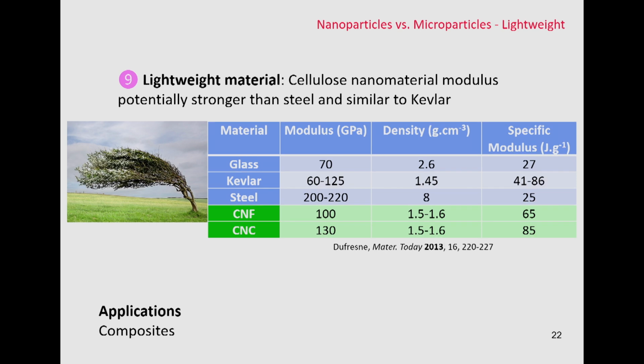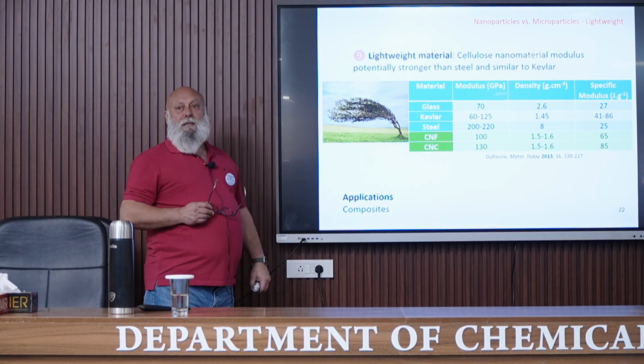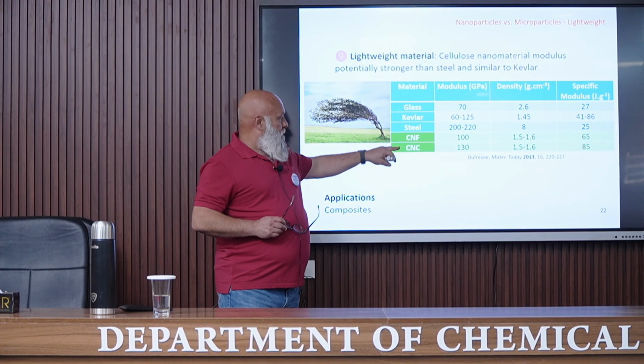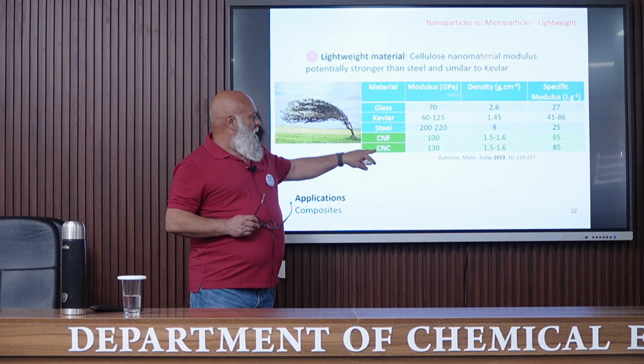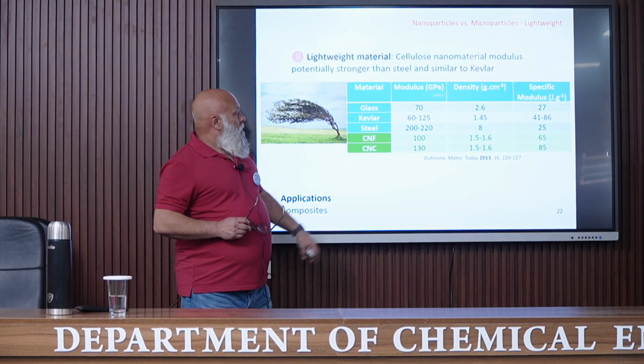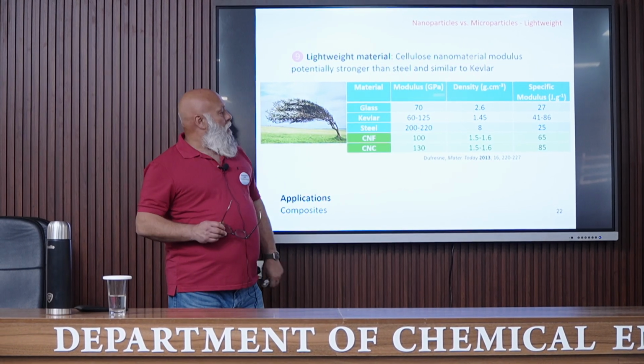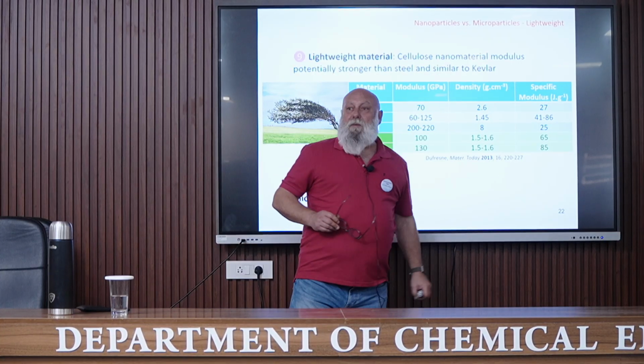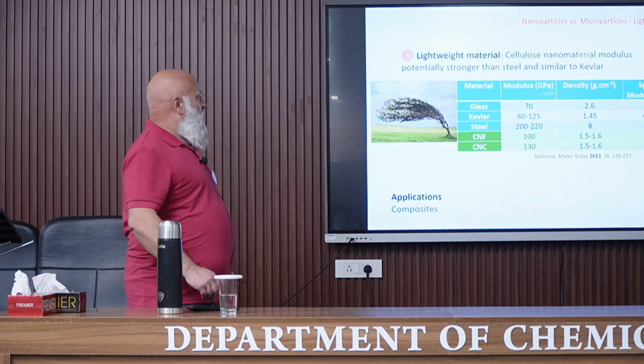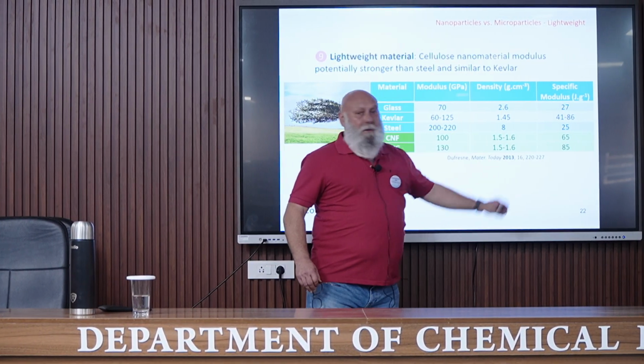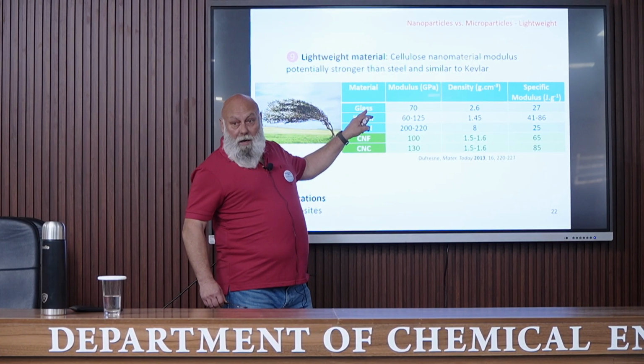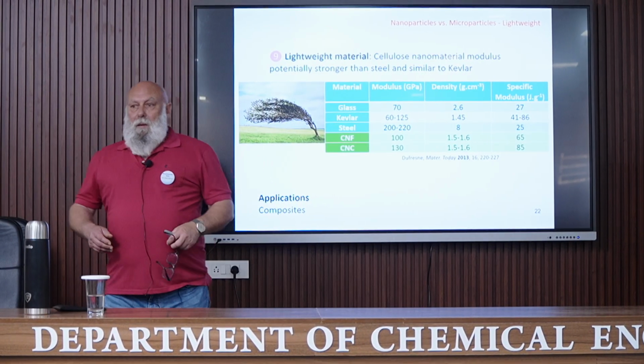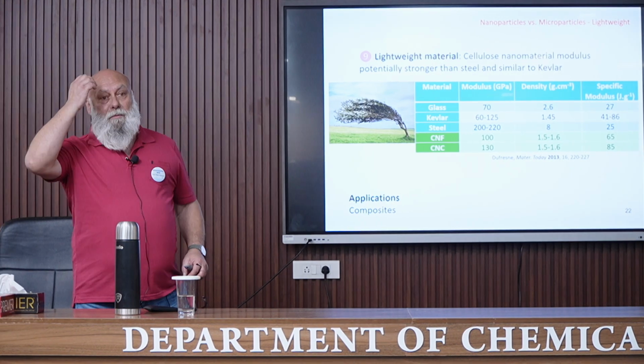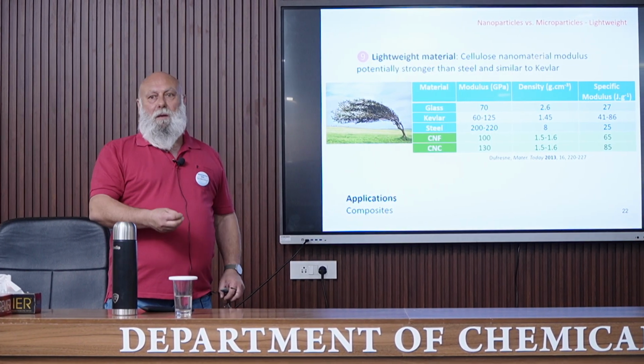So cellulose or other polysaccharides are lightweight materials. And so it means, do you remember in the video it was explained that cellulose nanomaterial modulus is potentially stronger than steel. You have here a table in which you have different materials, so glass, Kevlar, steel, cellulose nanofibril, cellulose nanocrystal, the corresponding modulus, the density. For crystalline cellulose, it's between 1.5 and 1.6, and the specific modulus, which is the ratio of the modulus divided by the density. And what you can see is that for cellulose nanomaterial, this specific modulus is higher than for steel or for glass, and in the same range as Kevlar. And this is important for composite application because it's necessary to use reinforcement with a high modulus, but the density should be low also.